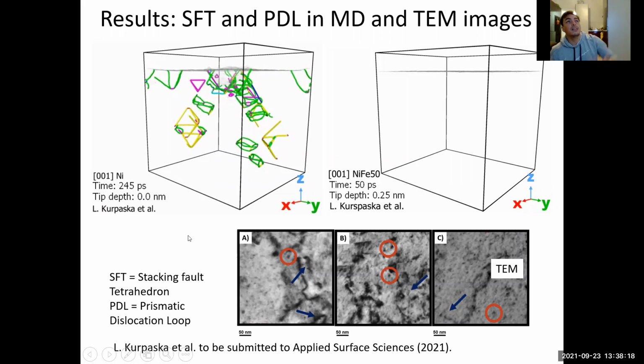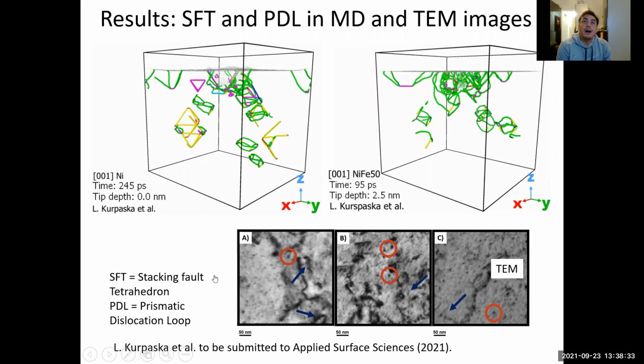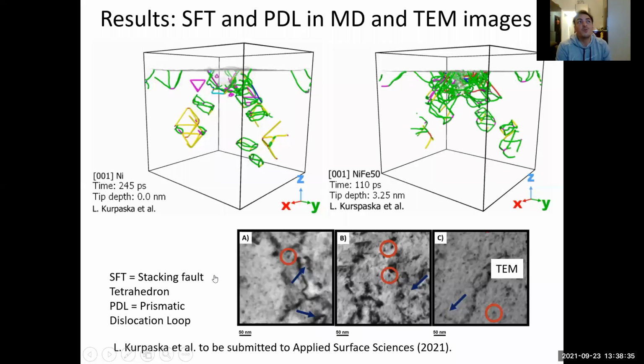This is only for nickel, and then we already reached the unloading process. So what is happening when you have 50% of iron in the material? Again, the dislocations are being nucleated, but then it is more difficult for them to propagate. And it's even more difficult to form the stacking fault tetrahedron.